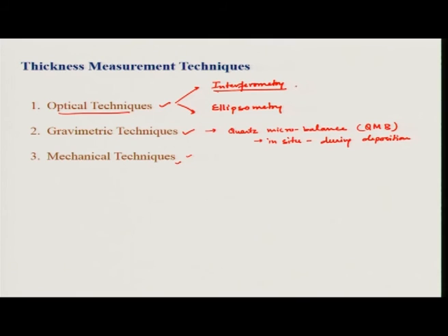Okay. Interferometry techniques are usually called optical profilometer. Okay. Ellipsometric techniques are usually used when you need not only thickness but also optical constants such as N and K. If you need to measure these properties as well, you can use ellipsometric techniques, and these are mainly used for dielectric films, where you need to know the dielectric constants which are related to these optical constants.